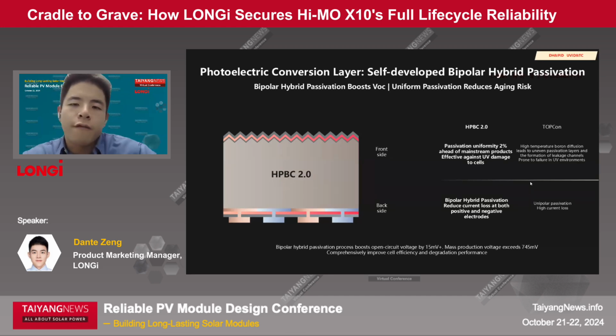But for our BC technology, firstly, we do not have high-temperature sintering on the front side, so we won't create any leakage channels on the front side. And for our backside, we do have channels, of course, but we have our bipolar hybrid passivation, which is very advanced and can reduce the current loss. But TOPCon just has the unipolar, their own tunneling oxide passivation at the backside with the N-type diffusion.